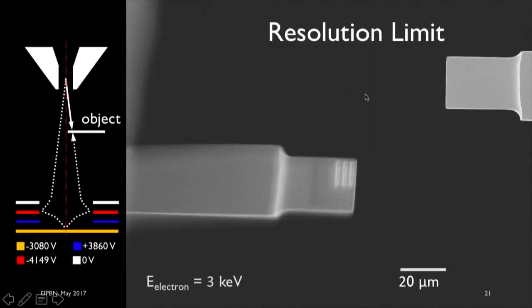When I move the actual cantilever to the left, the mirror image goes to the right, as you would expect. So just to have a better idea of the resolution of this kind of imaging, we milled out three lines using a focused ion beam on the bottom surface of this cantilever. Again, on the right, you see the actual top surface image, but you don't see any lines because this is the top surface, and we milled out those lines on the bottom surface.